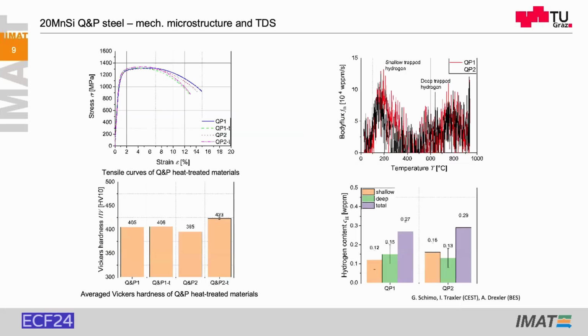Yeah, what was the outcome of different quenching and partitioning parameters? It's not too much influence on the mechanical parameters, yeah, sorry, the pointer doesn't work. Not too much on the hardness. Also the hydrogen content with TDS showing just comparable shallow and deep traps.